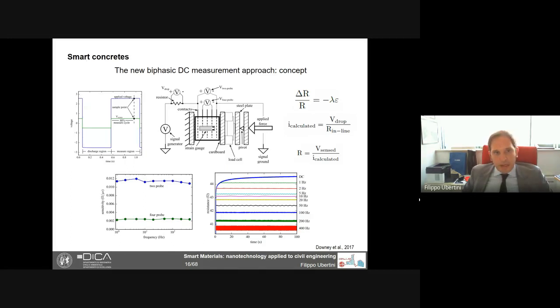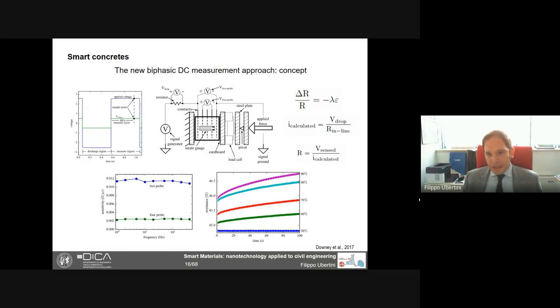And the way we do this is by applying the voltage input in the form of a square wave, where we have plus minus, for example, 2.5 volts in a single period of the square wave. And then for every period of the square wave, we just take one sample, one reading. And in this way, as you see in the bottom right, we completely remove the drift in time because of symmetry reasons, because the material stays the same time in the charge and the same time in the discharge part of the input. And the duty cycle of 50%, which means same time in the discharge and same time in the measure region, is actually the best value to get no polarization, as you see in these results.